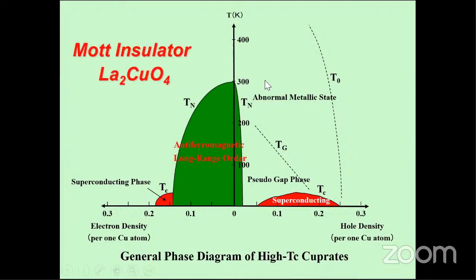So basically, the high TC is a Mott insulator because this is ceramic. It's a magnet. So then we have to dope the carriers, as electrons or holes. Then we can see the superconducting state, killing the magnetic state. So then the carrier doping creates the superconducting state like that. So then the original state is the magnet.